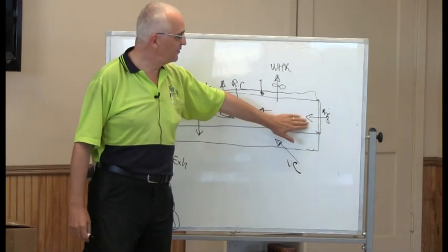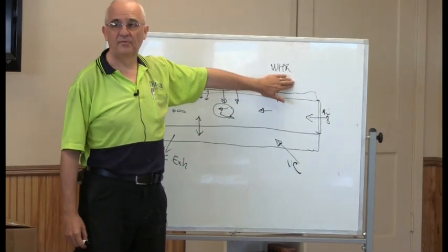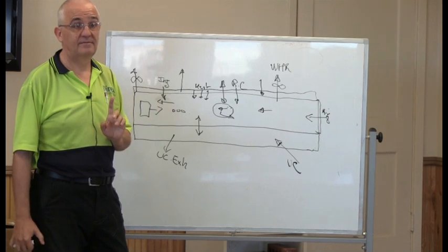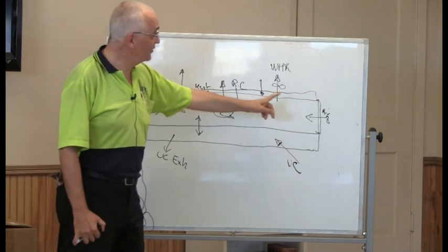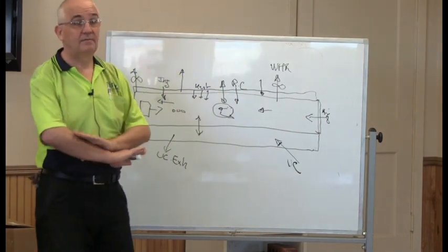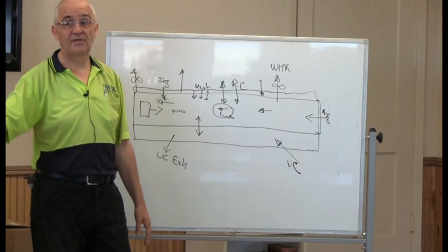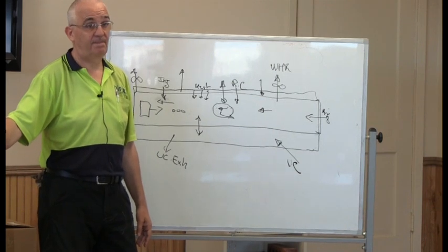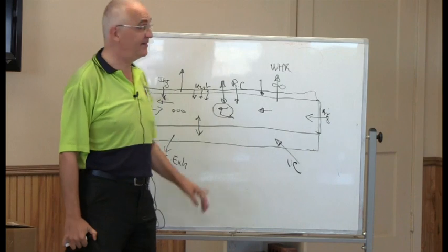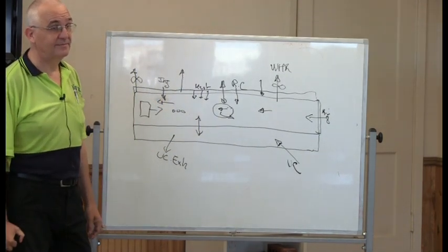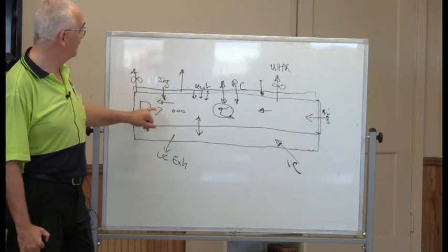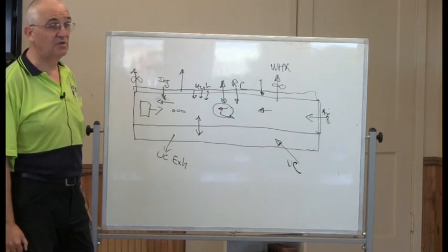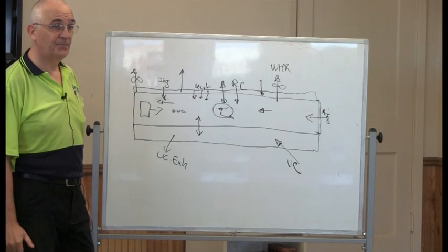If I double the quantity of air here and I double the quantity of air I remove there, I will have exactly the same pressure as with the single volume of air. But the cooling conditions here are going to be completely different. So even though you read the same pressure, you don't have the same flow conditions. We agree on that? And it's the same for the exhaust pressure, etc. If I reduce the flow here and I reduce my speed, I will maintain exactly the same pressure. Does it mean I maintain the same flow conditions? No.